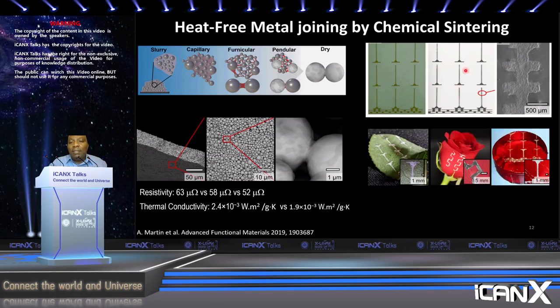Then we can take these printed structures and challenge ourselves to go to even more delicate structures. Here we start with a simple thing such as a leaf. We're in Iowa, we are farming country, so it's important for us to keep our farmers engaged. So we printed on a leaf, we printed on rose flowers, and then, thanks to a very nice reviewer who challenged us to think of even more delicate structures, we printed on a jello. The way it works on a jello is there's a density difference that allows the particles to settle on top of the jello. When you apply your etchant, you will actually get sintered particles, but you have to use a higher concentration of the etchant here than you use on a rose flower or on a leaf.